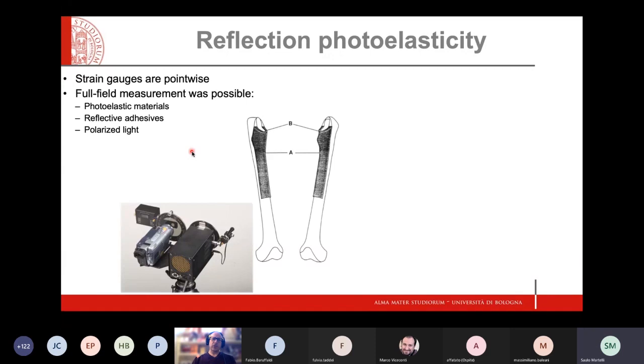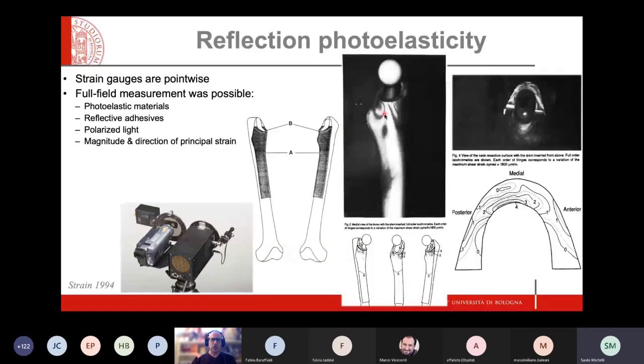We were not totally happy with strain gauges because strain gauges are measuring strain only where they are applied. So we started with a full field technique parallel with strain gauge. Essentially, this is a plastic material whose optical properties are affected by strain, and when it is bonded on the material with a reflective adhesive, a polarized light is crossing the material and reflected back. So by measuring this effect, you can observe fringes that show the magnitude and direction of principal strains. So this is how a hip stem was affecting the strain distribution in the proximal part of the femur, and it's a full field image. And also you see how it's distributed on the resection surface. So where strains are larger, how they are aligned, and so on. It looks nice, but it has a lot of limitations. It requires a lot of time to prepare, a lot of manual skills. It's time consuming, and it has limited precision due to the methodology and to the reinforcement effect.